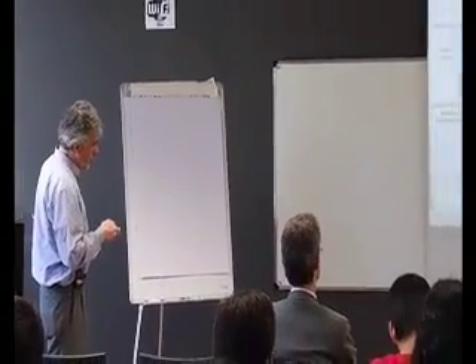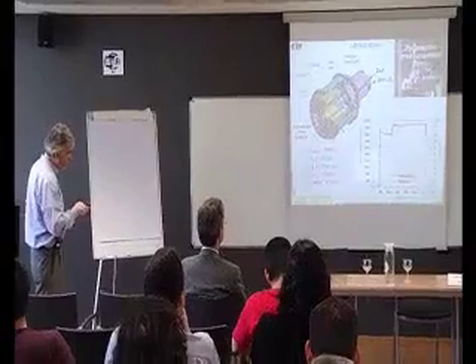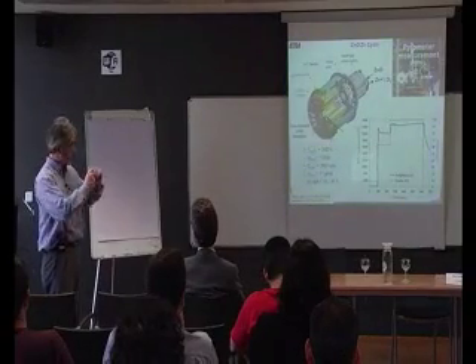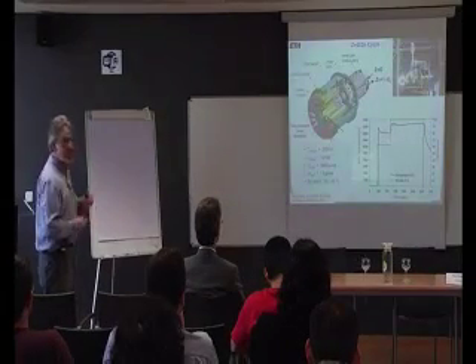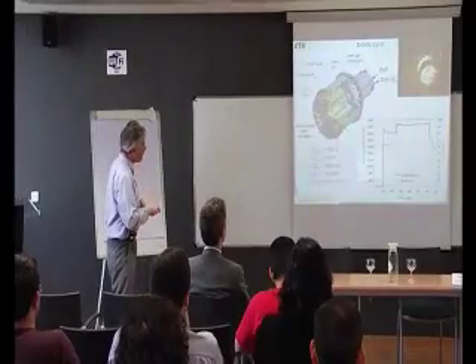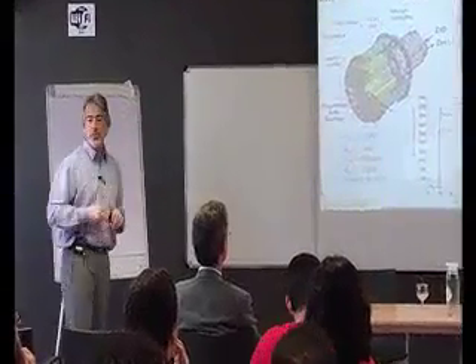Typical results: nominal temperature 2000 K. We are introducing 10 kilowatt of concentrated solar power with a peak concentration at the aperture of 5,800 suns. That means 5,800 kilowatt per square meter over the small aperture. By the way, the aperture is 6 centimeters in diameter, so we are putting 10 kilowatts over a 6 centimeter opening. Here you see the mass flow rate of the zinc oxide. And when we collect the zinc downstream, we condense and collect, we see that the particles have a zinc content that varies between 50% up to 95%.